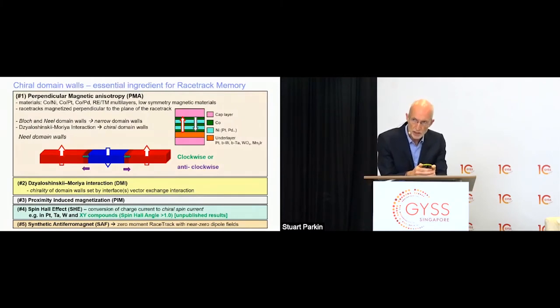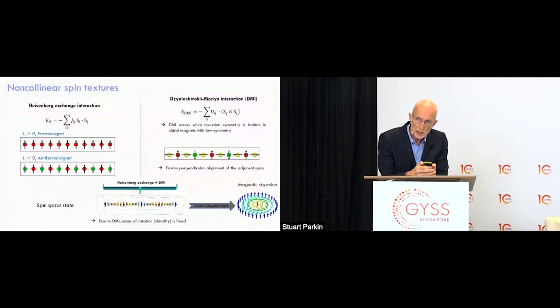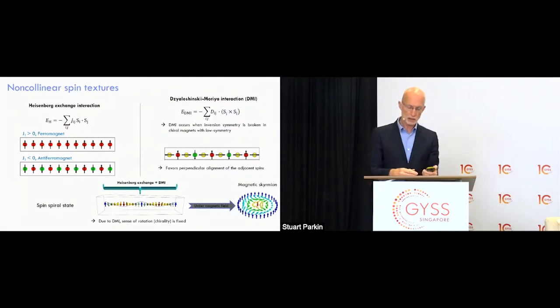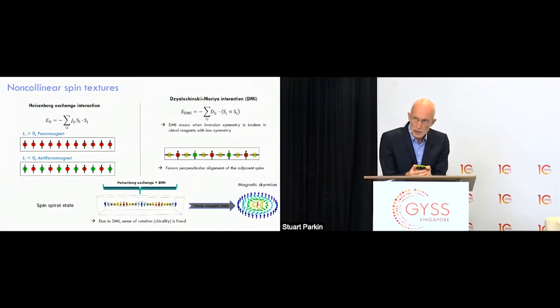So we would build the racetrack not from a single cobalt, nickel, cobalt superlattice, but from two. I just want to remind you then about this Dzyaloshinskii-Moriya exchange, which also leads to chiral domain walls and more complex non-collinear spin textures, which, if there's time, I would like to discuss. On the left side here, you can see the basic exchange mechanism, which is called a Heisenberg exchange, causes in some materials the magnetic moments of the individual atoms, such as in cobalt, nickel, iron, to be oriented parallel to one another. And this is a Heisenberg exchange. In some materials, that exchange can be negative, and the moments will be oriented not parallel, but antiparallel. This is an antiferromagnet, for example, nickel oxide.